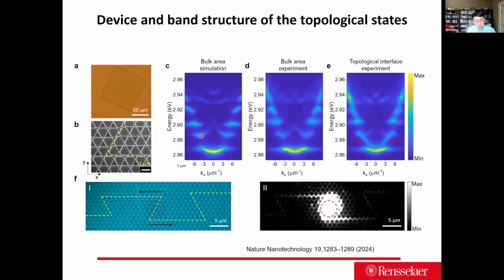And then the bulk simulation shows that such a crystal will have a nicely predicted band structure, and the bulk experiment also matched the simulation. And then the topological interface experiment specifically measures the band structure at this interface. We can see this topological edge band start to form in the band structure, and by selectively pumping the edge area, one can see this nicely confined topological edge mode propagate around the C3 sharp turn corners without backscattering.